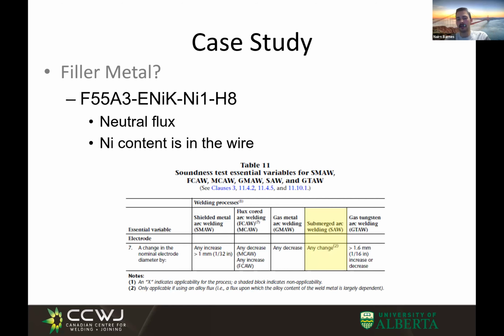And one of the things I wanted to highlight here, because this is an important thing to talk about when you talk about submerged arc welding, is that we're going to look at the essential variables here. So when we use this wire and flux combination, we choose to use a neutral flux. So I'm sure you guys have talked about neutral versus active fluxes when you talked about subarc welding. But really what we want to do here is have the wire doing the alloying and not our flux, because active fluxes can have very, very good effects in welds. They can also have some fairly negative effects in welds.